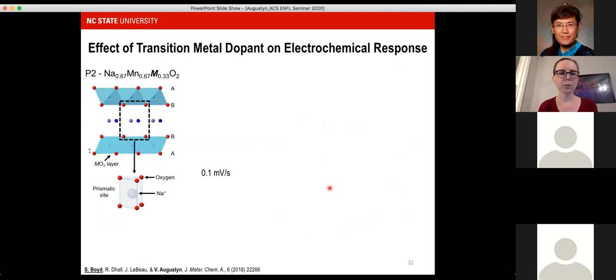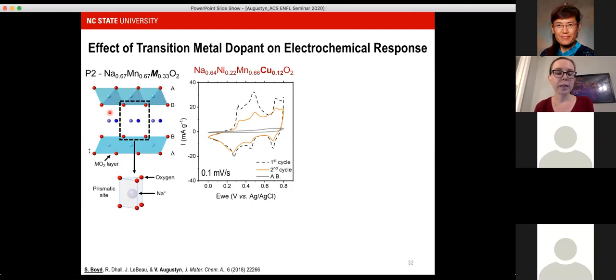In particular, we were interested in looking at these very well-known layered sodium metal oxides called the P2 oxides. They're called P2 because the sodium is in a prismatic site and the oxygen stacking sequence is this ABBA sequence. The structure is quite flexible in accommodating different transition metals in what's called the transition metal region. We chose manganese-rich compositions and then varied what the other dopants were. The aqueous sodium ion intercalation electrochemistry was quite different, depending on what that dopant would be.